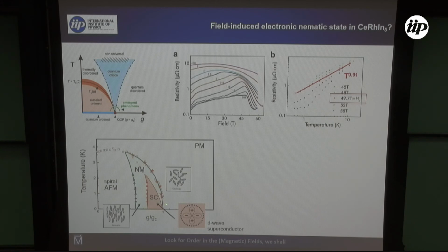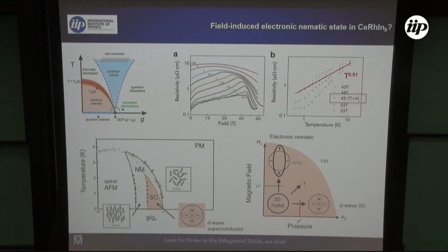One of them is a d-wave superconductor. The other one is a nematic state. So what we have here is a material that is initially partially hybridized because it's not completely local. The magnetic moments in the cerium positions are not fully developed because of some hybridization between the f electrons and the conduction electrons. How do we know that? Well, it is an antiferromagnet with a heavy mass.